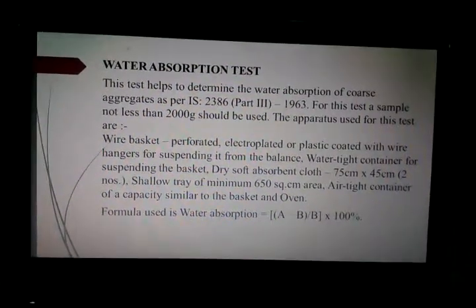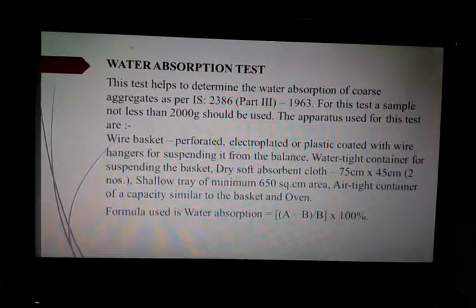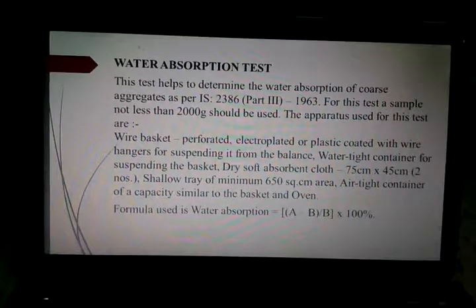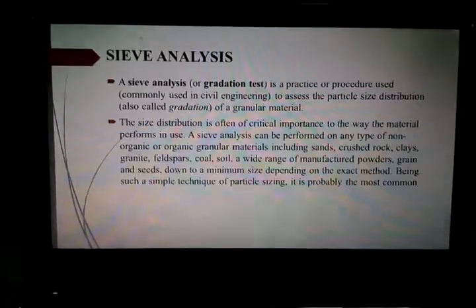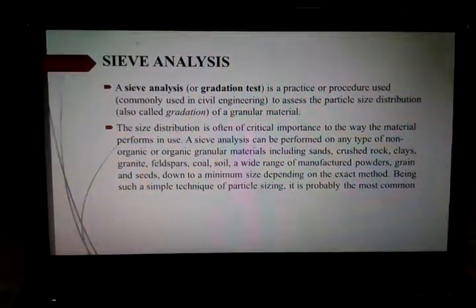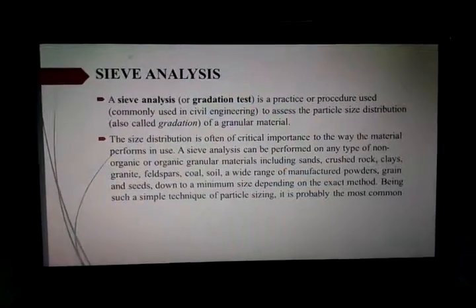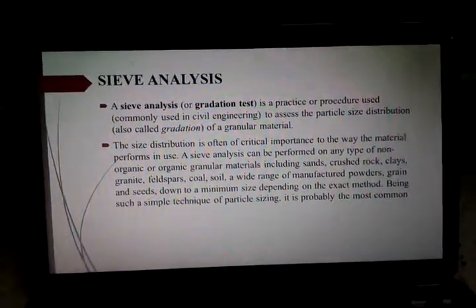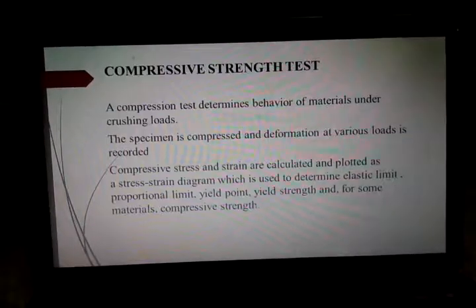Water absorption test. This test helps to determine the water absorption of coarse aggregates as per code IS 2386 Part 3 1963. The formula used is water absorption equals (A minus B) divided by B into 100%. Sieve analysis. Sieve analysis is nothing but the gradation test. It is a practice or procedure used commonly in civil engineering to assess the particle size distribution of granular material for both fine and coarse aggregate.